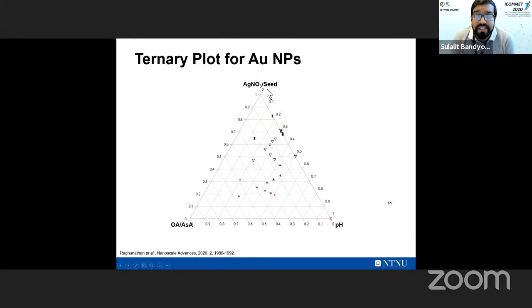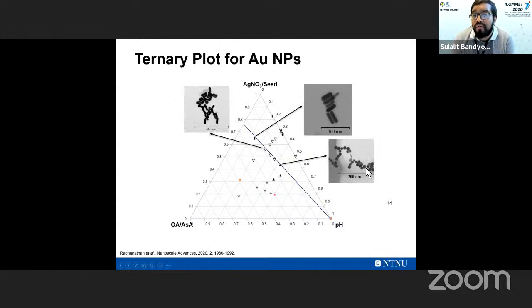So this is a typical diagram that we have now recently published for the first time in this literature, where we try to group the growth directing agents, the silver nitrate and the seed, on one vertex, the binary surfactant, which is also a reducing agent, and ascorbic acid, the main reducing agent, their ratio, and then the pH. Now, care should be taken here that the pH is a normalized pH, and therefore it can be plotted on a ternary diagram. What we have seen is that if we draw these different tie lines, we are able to go to different shapes.